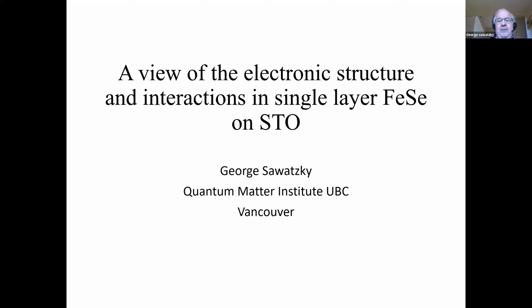So the single layer FeSe, iron selenide itself, of course, is also a superconductor. It doesn't have a magnetic transition. So we all feel that, hey, this is a nice thing to study. Transition temperature of bulk iron selenide is very low, about 8 degrees Kelvin, if I remember correctly. And it has a very, very low carrier density, a very low Fermi energy, and it has only Fermi pockets, only electron pockets, and apparently no hole pockets in it in the single layer type material.